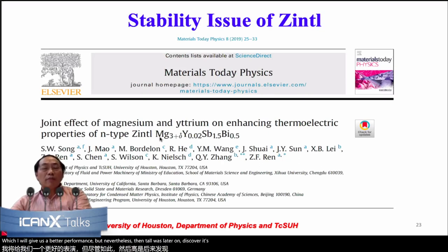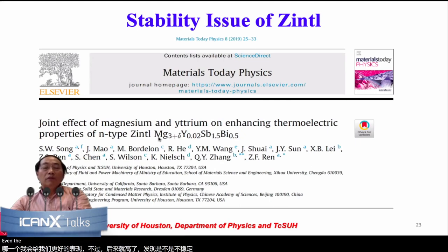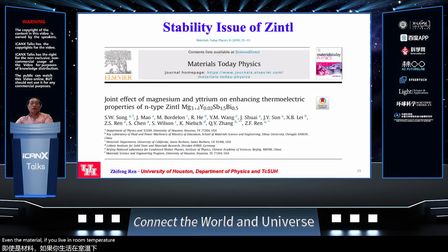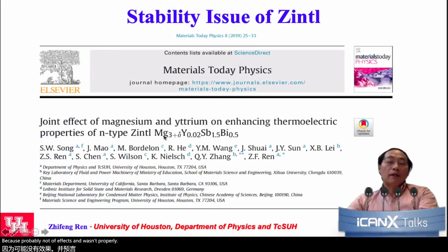But nevertheless, the Zintl material was later discovered to be not stable. If you leave the material at room temperature over a few weeks, the properties degrade, probably because of lots of defects and also probably the migration of the magnesium. And of course, now we understand what sorts of issues there are.